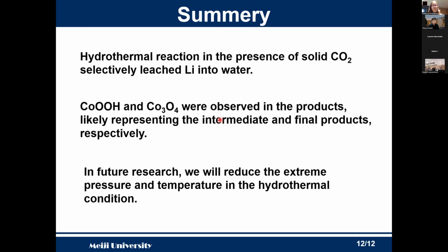Yes, it is very easy, but liquid carbon dioxide makes an upper pressure of about 5 megapascal, while the advantage of using solid CO2 is that it can make a pressure higher than 5 megapascal. So for this purpose we use solid CO2.